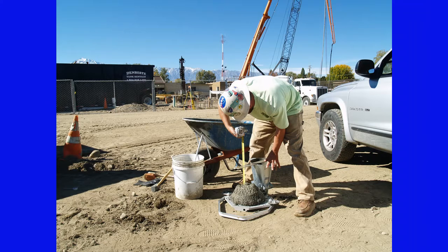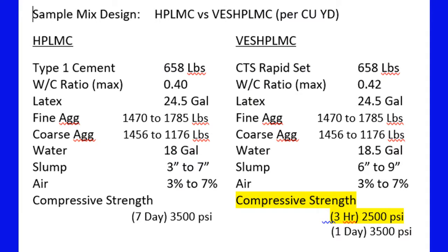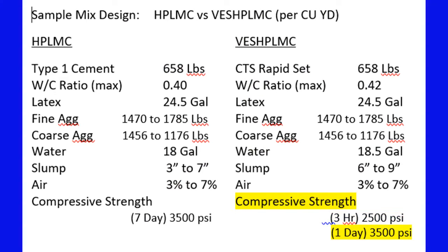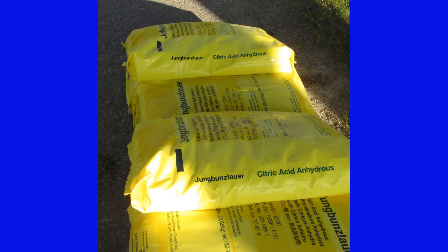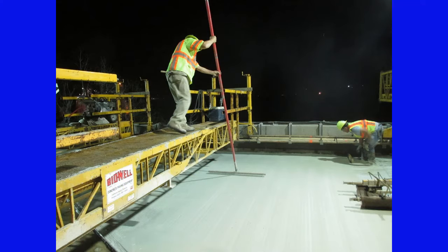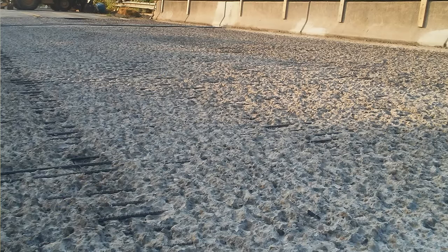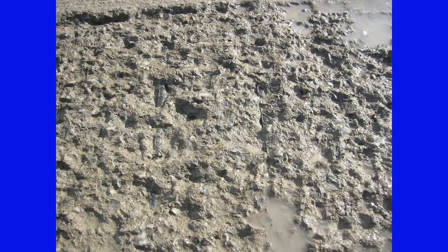VESHPLMC can be expected to gain compressive strengths of 2,500 psi or more within 3 hours during warmer temperatures, with a minimum one-day strength of 3,500 psi. A retarder such as food-grade citric acid can be used per the cement manufacturer's recommendation to help temper the set time and allow a little more working time for the finishing. As with normal HPLMC, surface preparation and deck saturation prior to the pour is critical.